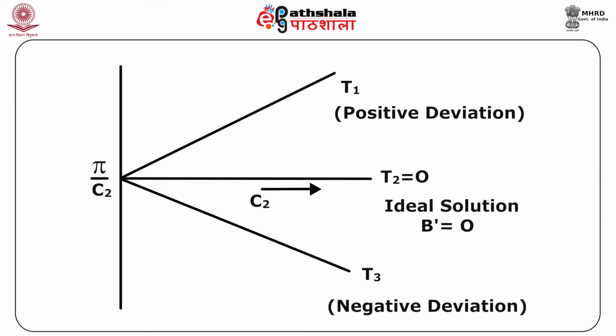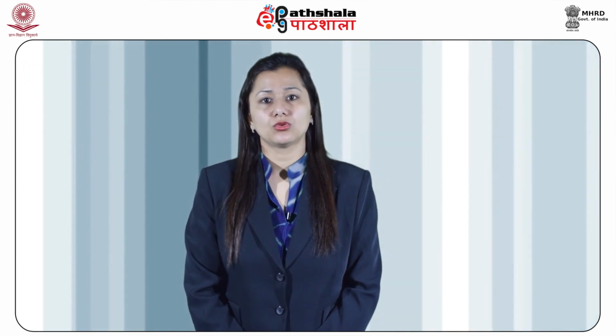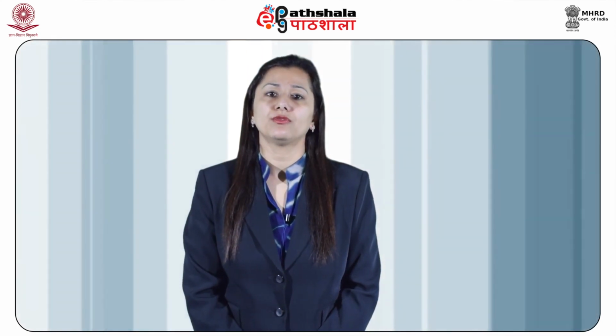Figure shows the plot of reduced osmotic pressure pi by C2 versus C2 at different temperatures. The temperature at which, for a given polymer-solvent pair, the polymer exists in an unperturbed state is termed the theta temperature. This is also the temperature at which the second virial coefficient becomes 0. In the figure, T2 is the theta temperature. This temperature is also called the critical solution temperature for a polymer of infinite molar mass.